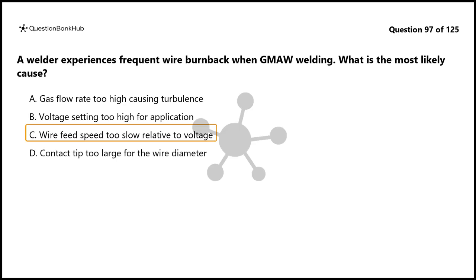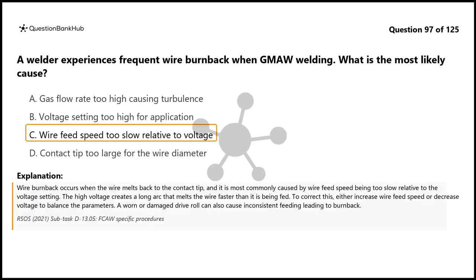Wire feed speed too slow relative to voltage. Wire burnback occurs when the wire melts back to the contact tip, and it is most commonly caused by wire feed speed being too slow relative to the voltage setting. The high voltage creates a long arc that melts the wire faster than it is being fed. To correct this, either increase wire feed speed or decrease voltage to balance the parameters. A worn or damaged drive roll can also cause inconsistent feeding leading to burnback.